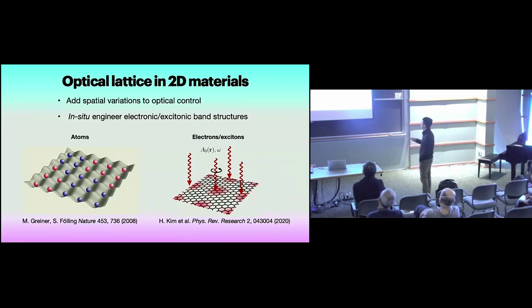spatially patterned field to create some flat band in graphene structures. This adds some advantages because now you can dynamically modulate this periodic potential and look, for example, for phase separations. So not only for 2D materials, but also perhaps very interesting for other quantum materials. Of course, one of the challenges is that for atoms, we can just interfere two free space beams. The periodicity can be pretty large, comparable to the wavelengths. Here, for solid-state systems, we want this periodicity to be quite small, below the diffraction limit, similar to a Moiré, right? So where we can see a strong effect.